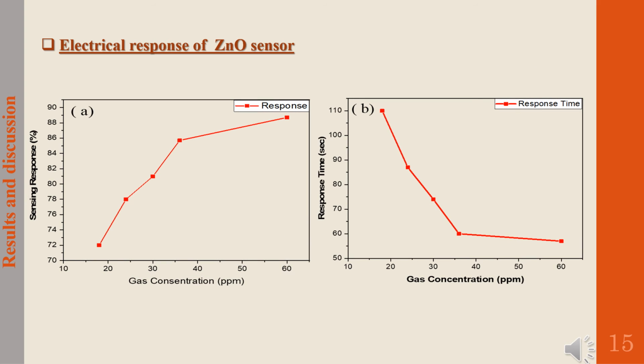The following figure shows the responses and the response times for all concentrations of ethanol gas. The response seems to increase with increasing ethanol concentration, specifically at 60 parts per million. The response time is less than 60 seconds.